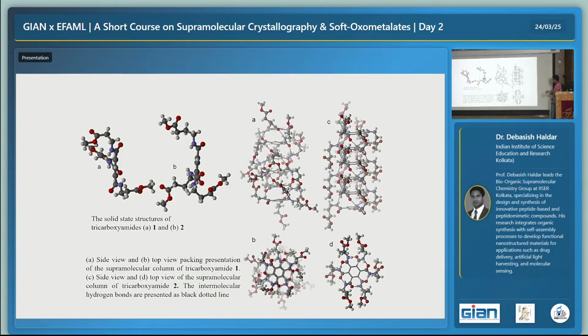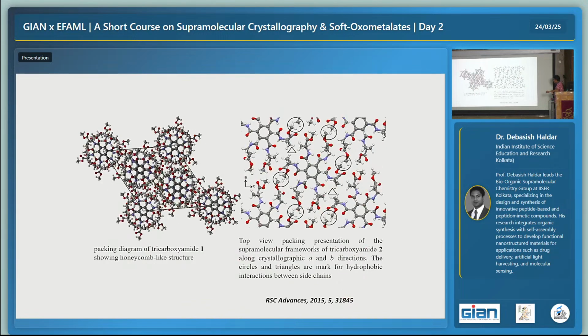Okay, so this is the crystal structure for both compounds. Once again for both compounds, the C3 symmetry is lost, so two of the amino acid functional groups are on one side of the central benzene ring and another one on just the opposite side of the central benzene ring. But somehow they manage to form three-member intermolecular hydrogen bond stacking and make a columnar structure. But in higher order packing, we have seen that there is a honeycomb-like structure for the beta amino acid, but for gamma amino acid there is a hydrophobic interaction that actually helps to form the molecular gel in different organic solvents, which is missing in the beta case.